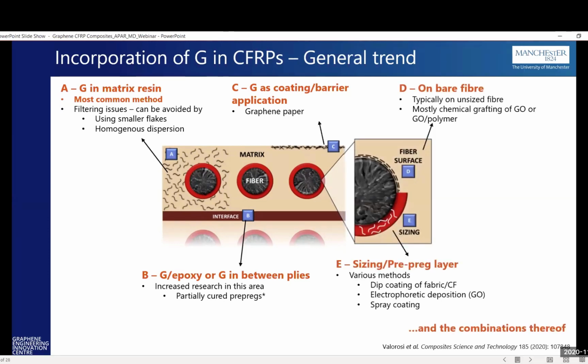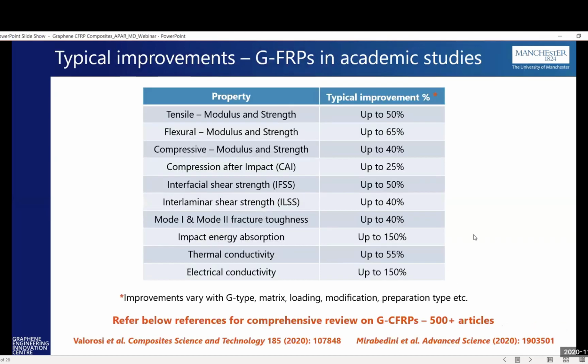Or the other method is just to modify the surface of the carbon fibers themselves, either by grafting graphene or graphene-based materials directly, covalently, to the carbon fibers, or you could possibly modify the actual sizing material by adding graphene or graphene oxide-based materials to it. So that can actually act as the interface between the carbon fiber and the matrix. And typically, combinations of these are quite variedly studied. Modifying the matrix and also modifying the surface of the carbon fibers seems to generally work for the FRPs.